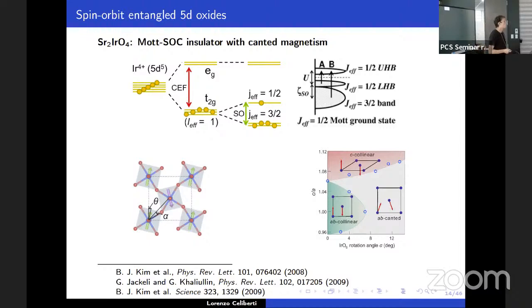So I also have a question. In this case, you consider the spin-orbit coupling first, make this a half-filled band. Then you apply the Hubbard U so that you have the half-filled band. But in this case, you need to have the spin-orbit coupling stronger than the U from the beginning. You mean like to do the opposite, have the U interaction stronger first and then turn it on? As far as I know, this has been done with DFT. You can switch on spin-orbit coupling, do a calculation, then also switch on the U correction, but it's not something that you do one on top of the other in successive steps. So basically, you have both.